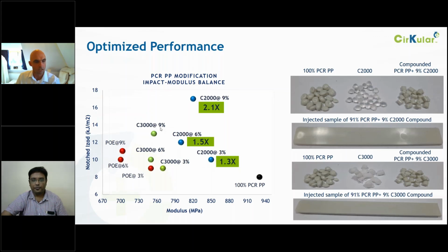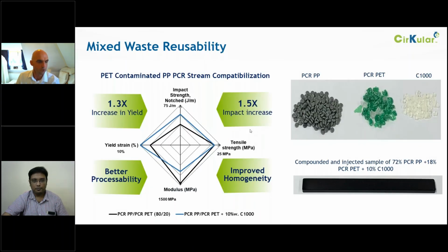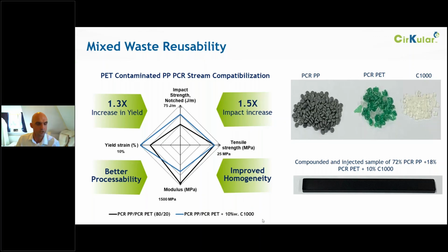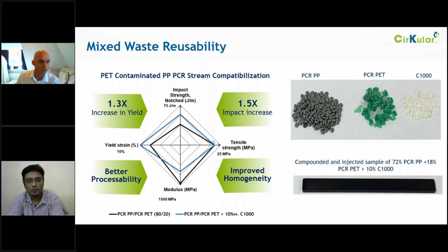Depending on the processing conditions, you can choose between the different grades. The C3000 is an unhydrogenated styrenic block polymer. C2000 is hydrogenated, so that one is a bit more powerful if you, for instance, process polypropylene, because you can go also to a bit higher temperatures. There's another example. This is actually looking at two pretty much completely incompatible streams. This is looking at the compatibilization series, so the C1000 series, and these polymers can actually make the incompatible compatible. So if you take a PCR polypropylene, a PCR PET, and a C1000, you can get pretty good properties, and even combine the two streams, which can be beneficial, and it's showing that you can sometimes live with some contaminants.